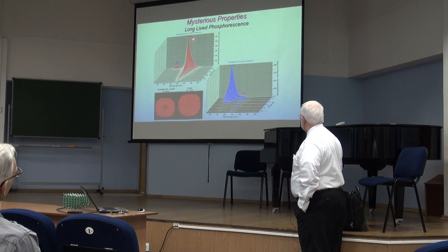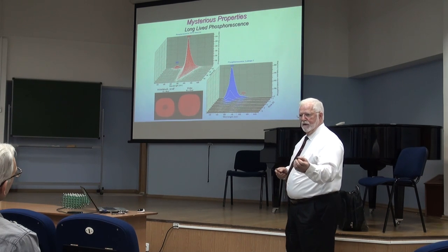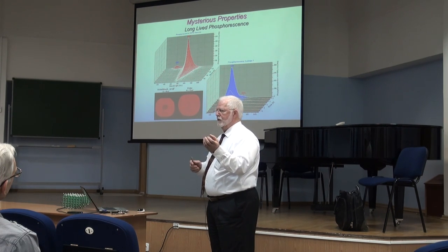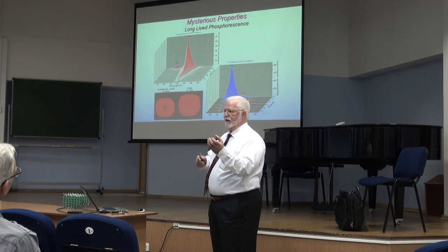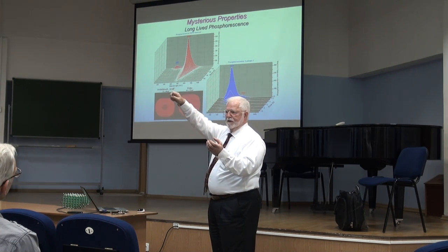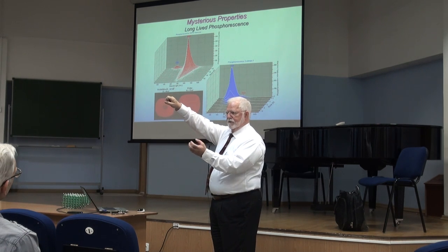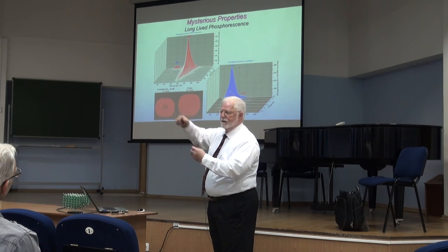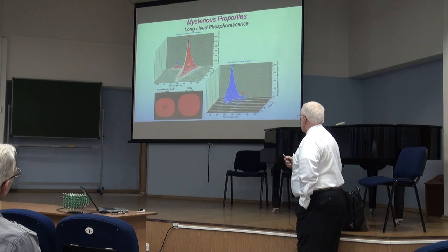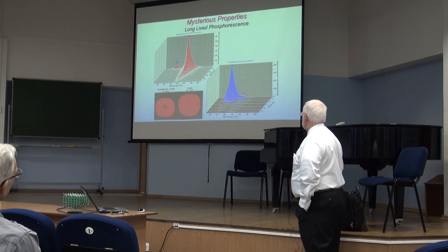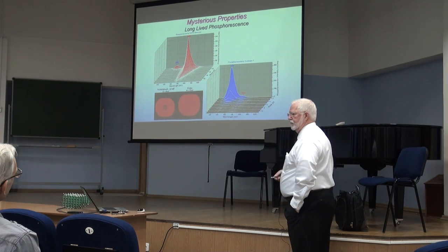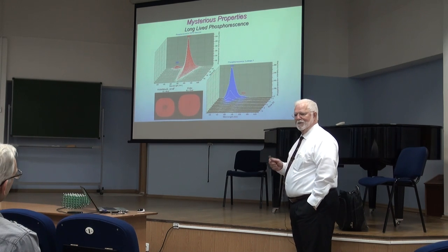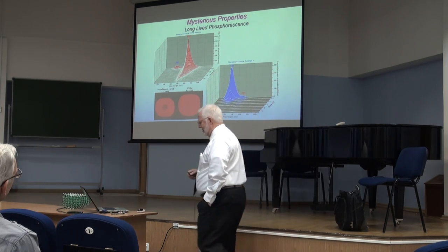What we think this is, because these are all blue diamonds, we know they have boron in them. We know boron is an acceptor. There's a well-known process in semiconductor physics called donor-acceptor pair recombination. This is where I pump charge up into a donor state. It sits there, isolated, and I have an acceptor state sitting nearby, and all of a sudden the electron and hole recombine and give off light. That's what we believe this is. Unfortunately, because we know the energy of the acceptor state, we can work out from the spectroscopy the energy of the donor state, and to our surprise, that does not match any of the known defects in diamond. So we're still studying this.